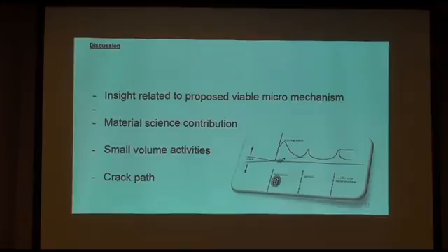Now, according to this, we follow now a slip-stick road. And the slip-stick road summarizes in a schematic way that every time we are moving a little bit, we establish a higher stress field due to the crack tip moving, the dynamic of the crack tip, and altogether we are going dip by dip, moving with the slip-stick road in a discontinuous way.